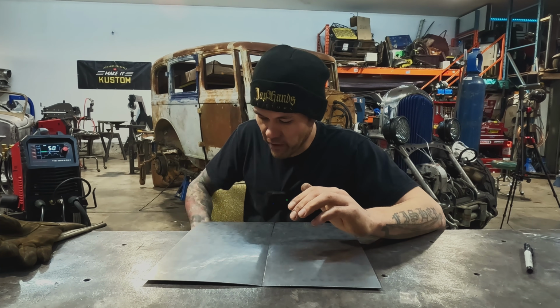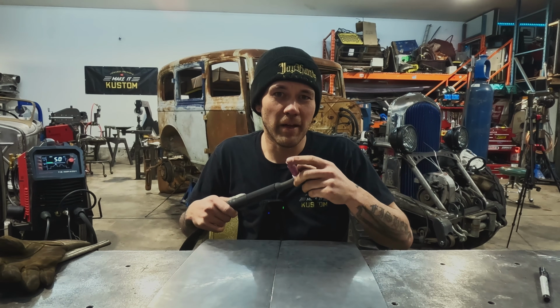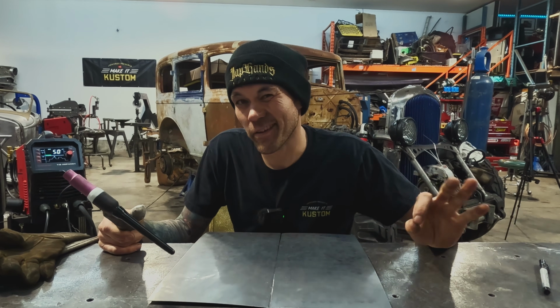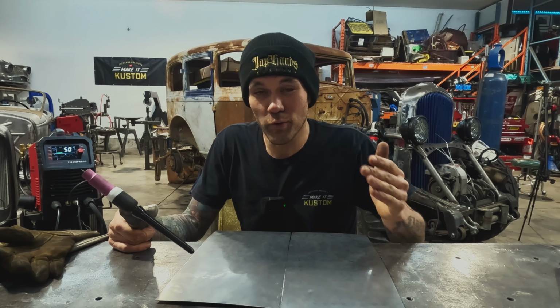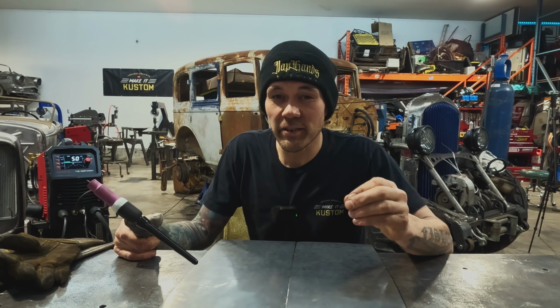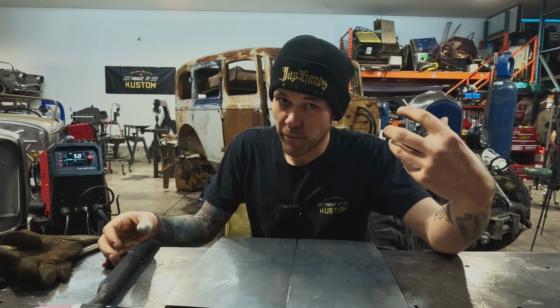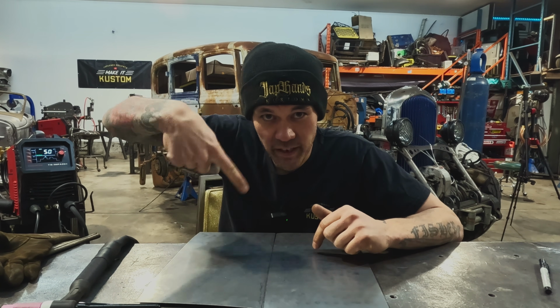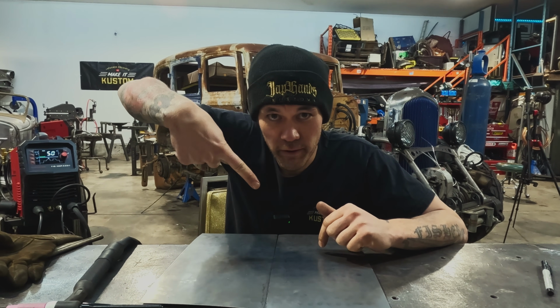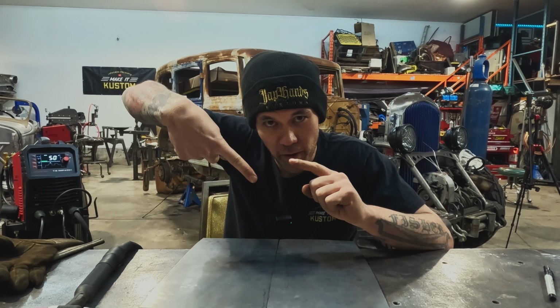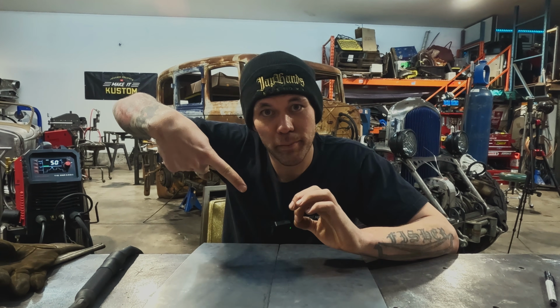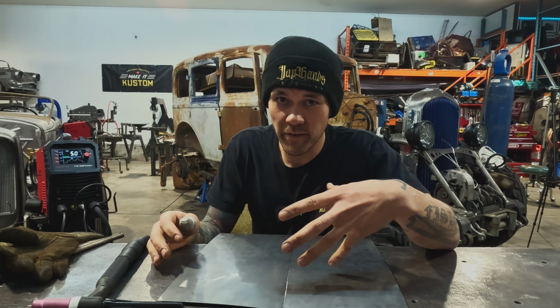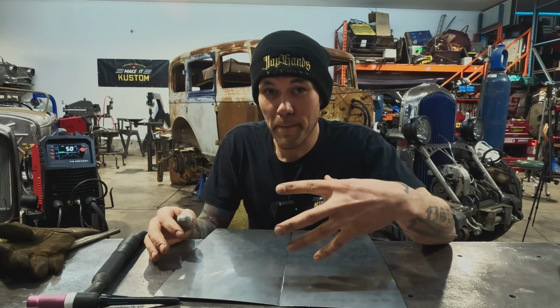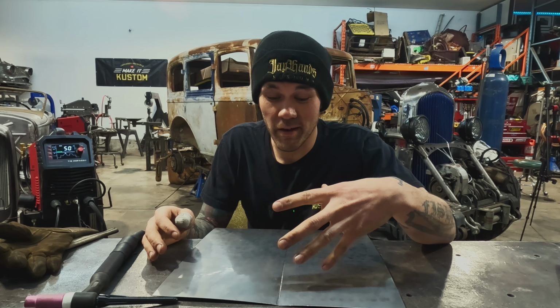What I'm going to use is a 1/16 tungsten, and I'm going to use .040 filler rod. Another trick of the trade is that you do have to use a very thin filler. The advantage of using a thin filler rod when you're doing thin material is that, like I was talking about before, you're not adding more heat than you need. So I'm watching my puddle, because you can see it. I'm going to be in the direction of travel as I'm welding, and I'm watching the puddle, and if the puddle looks like it drops a little bit, I'll add a little bit of filler. If you're a beginner and you want to TIG weld sheet metal, this is the meat and potatoes of it. This is what you need to know. You've got to know all of it.